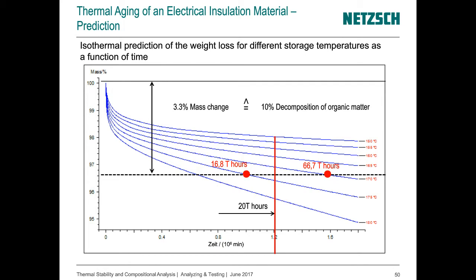decomposition of organic matter. We have seen that the total mass loss of organic matter was about 33%, so that means 10% is 3.3%. Now the question is how long does it take until 3.3% mass change is reached during isothermal storage at a certain temperature. A side condition was that this time interval should be longer than 20,000 hours.